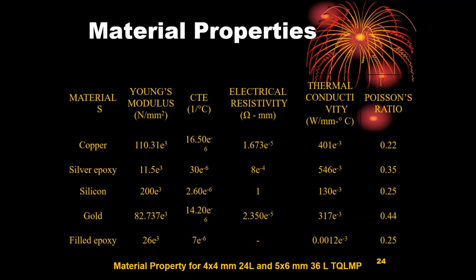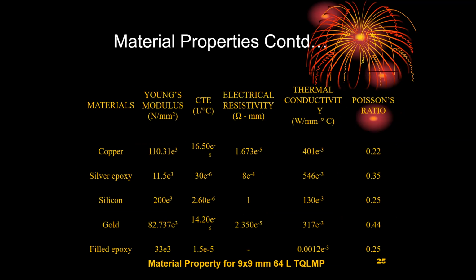So when we do an electrical to thermal analysis, a coupled analysis, first we have to take into account the electrical resistivity and thermal conductivity. And then when you do what is called thermal to structural analysis, we had to take into account the CTE, Young's modulus, and then the Poisson's ratio effects within maximum permissible limits. That's from MOT till the room temperature. We have not done any sub-zero or freezing temperature analysis, might be worthwhile later. So these are some of the material properties that we considered, they are given.